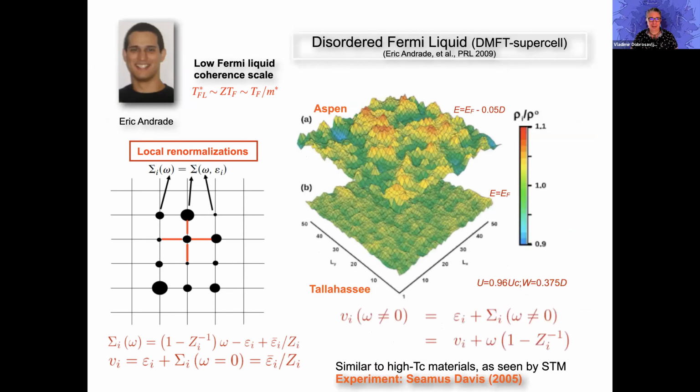Okay, thank you. So now, if we go further, I want to show you in real space what happens to how the system becomes inhomogeneous when we add disorder. The Fermi liquid becomes inhomogeneous, and I can plot it in real space. This is done now not in CPA but in a supercell calculation. Again, we have different site energies on different sites. We'll have different renormalized disorder potentials, and as a result, the local density of states, or the wave function amplitude, which can be measured directly by STM, can be plotted in real space. And we find that at the Fermi energy, it's extremely smooth.